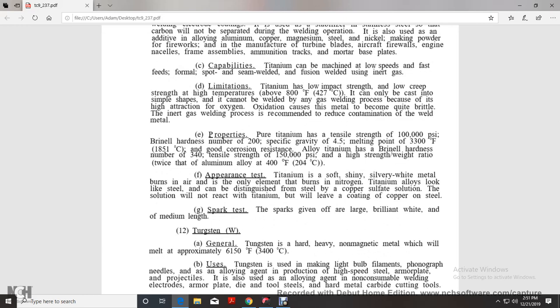Limitation: titanium has low impact strength and low creep strength at high temperatures above 800 degrees Fahrenheit. It can only be cast into simple shapes and cannot be welded with the gas welding process because of its high attraction to oxygen. Oxidization causes the metal to become quite brittle. The inert gas welding process is recommended to reduce contamination of the welded metal properties.